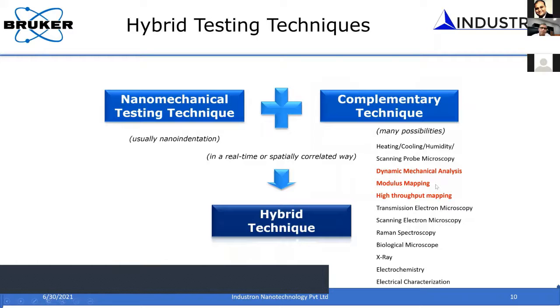So in my talk, my title is hybrid testing technique. What I mean to say is basically, along with this nanomechanical or micromechanical testing technique using this indentation probe, you can also combine it with something else. For example, like I mentioned about in-situ SPM imaging. If you can combine the in-situ SPM imaging with the hardness measurement using indentation, I will call it a kind of hybrid technique. Sometimes you can combine with, for example, Raman. In one of my examples, I'm going to present how you can use the Raman microscope to identify the chemistry of the surface, and then couple it with a mechanical property measurement. How you can do that? Okay, that's why I'm calling it a hybrid technique.